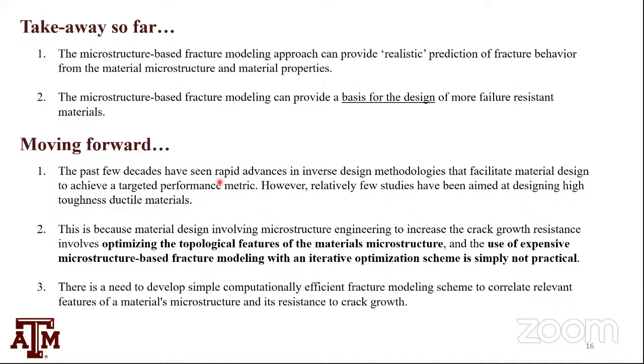Now, a lot of focus has been on improving elastic modulus and yield strength of the material, and nothing much on high toughness. The few papers on this topic focused on getting, in a homogenized sense, how much volume fraction of inclusion I should have. But there is some work done in that regard, largely because optimizing microstructure to enhance a material's crack growth resistance requires optimizing topological features of the material microstructure.